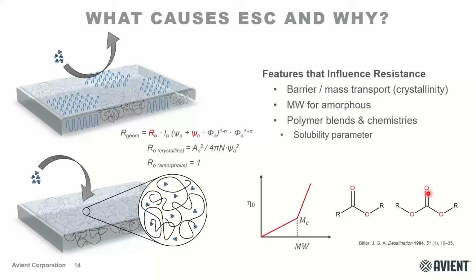And so you might be thinking, well, what can we do to try and influence the resistance of our material? And so I think the first thing to bring up when it comes to environmental stress cracking resistance is that crystallinity can go a long ways to improving a material's resistance. And the reason that crystallinity helps in environmental stress cracking is because it presents a barrier to the uptake of the solvent or the chemical reagent that it's being treated with.